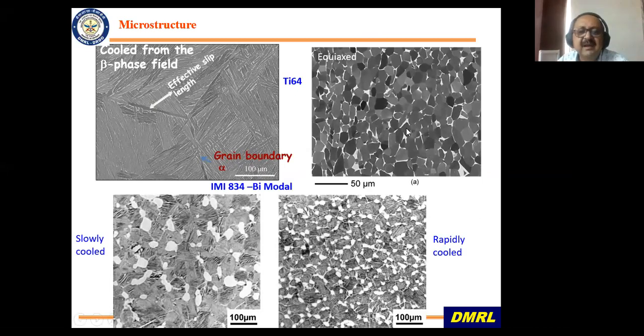Again, I'm showing the same microstructure. I did not explain, this is a beta process structure, beta treated structure. Big beta grains, ductilities are lower, but fracture toughness is better, creep is better. This, you can see, is an equiaxed microstructure, higher ductility, lower fracture toughness, lower creep, good fatigue and all.